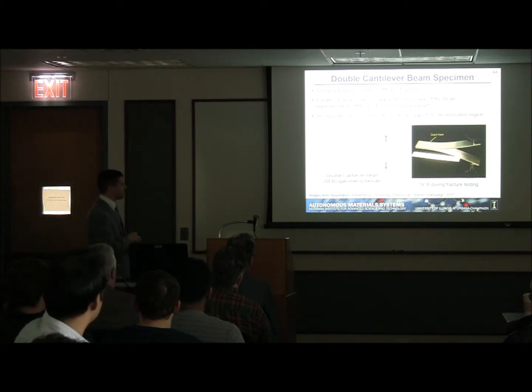The sample geometry we chose to employ is the double cantilever beam specimen. The double cantilever beam specimen is one where we have a composite beam loaded in mode 1 fracture. This schematic is representative of that, where we have a composite beam and a pre-cracked region, and we can load the sample up in these two hinges in tension, and that will force a crack to propagate along the midplane of the specimen to create a delamination damage. This schematic is one that I took from Brett Curl's thesis. Jason's work here is a double cantilever beam specimen we tested. Why we wanted to do this is that it creates a delamination crack at the midplane of the beam, representative of something that we might see during impact.